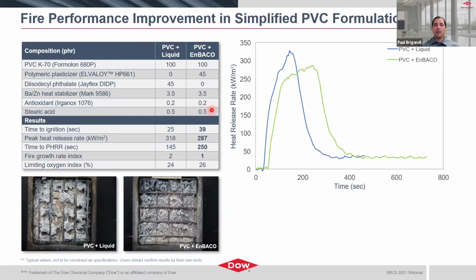So what we look at here is a cone calorimeter. This is just an example of the material after it has been burned. You can see that both are obviously very burned up, but there is more material left with the polymeric plasticizer. And when we start looking at the data and the results, there are a couple of key points that we want to highlight. The first is time to ignition.